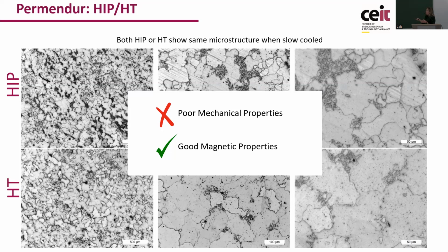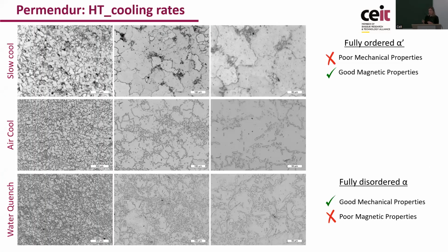So the objective, as I say, was to try to have these magnetic properties, but not lose all the mechanical properties. So the study that we did was to try to change this cooling rate and see how the microstructure was developing and how this was helping to increase or reduce the properties. So there were three cooling rates: the slow one that we already saw with the big alpha prime grains, and then one intermediate that was called air cooling, and the fast water quench cooling rate.